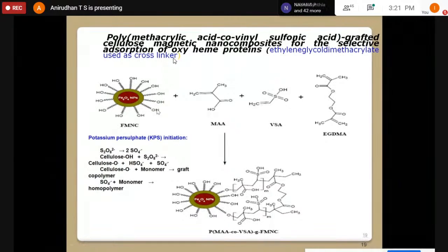Usually the primary alcoholic OH group associated in cellulose is highly reactive. So these highly reactive radicals like HSO4 or sulfate negative radicals remove one hydrogen atom from the primary alcoholic OH group of the cellulose. Your product is macro radicals like cellulose O dot. And this macro radical is highly reactive, then that macro radical may react with your monomer like methacrylic acid, vinyl sulfonic acid in presence of a cross-linking agent, so that your product has an interpenetrating network or a polymer network. So you have cavities or porosity, you can improve with your choice of the quantity of cross-linking or different types of cross-linking that you can utilize to improve the properties of your material.